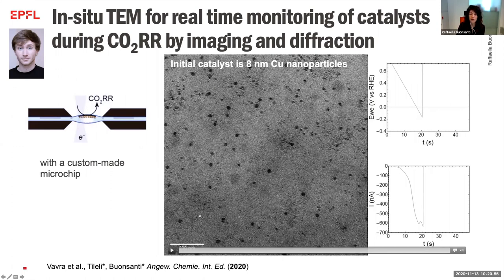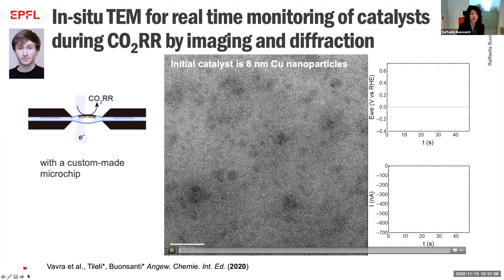So what we observe, I will run, so you don't see these initial 8 nanometer particles because they are too small when there is a liquid in between, but you clearly see that they start growing as the reaction proceeds.